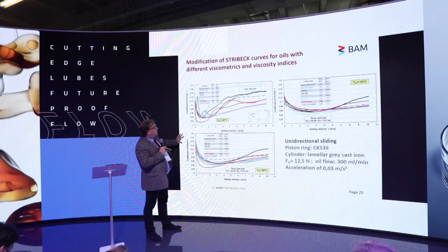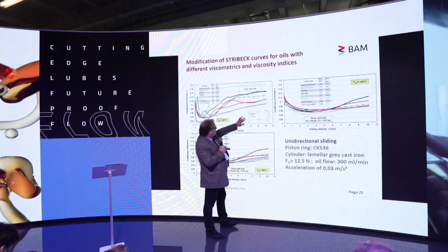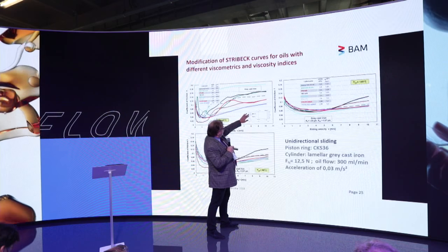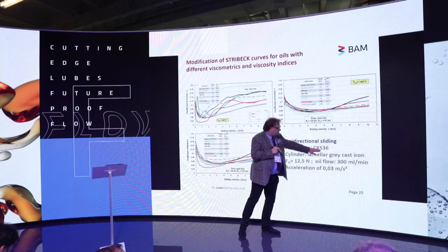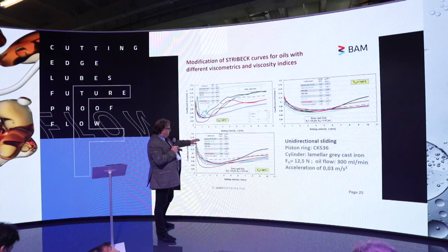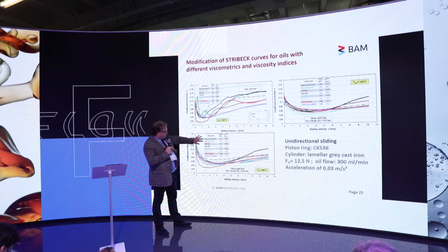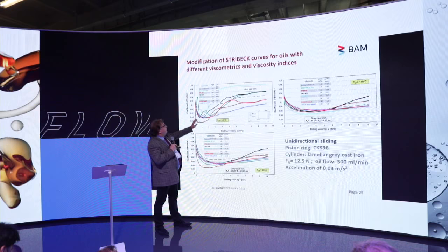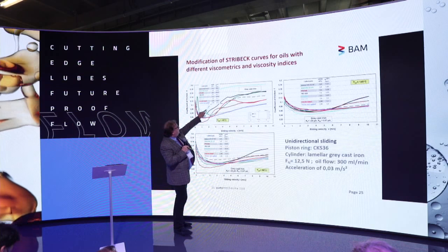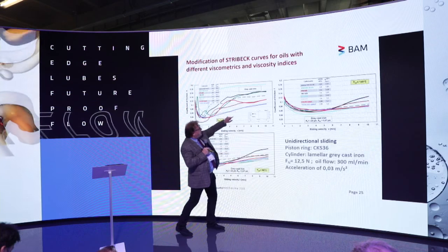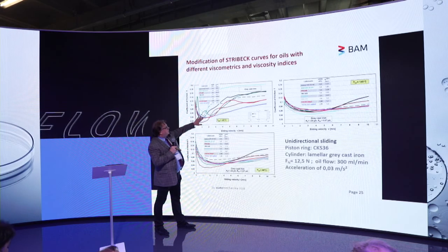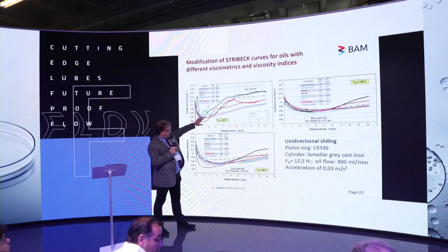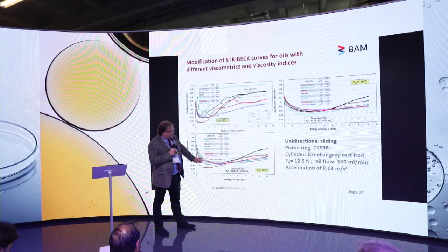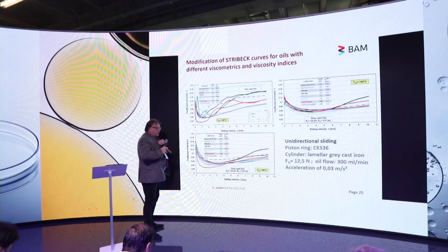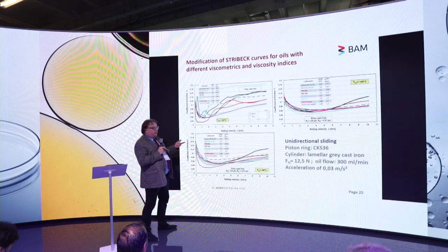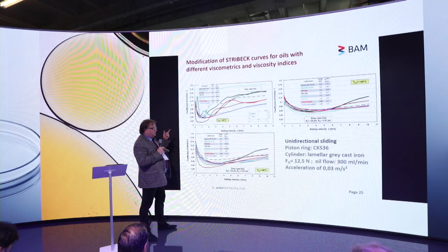What does it mean for the oils? If you look at a gray cast iron liner and a piston ring coated with a chromium alumina coating, and here you have different types of oils: factory fill oils, hydrocarbon, polyglycols. The factory fill, the gray and the green, at room temperature, high friction. You take a polyglycol, you have much lower friction at room temperature. At high temperature, the differences are not so big, but there are some differences. So changing the chemistry, changing the viscosity reduces friction for the future, but these are new chemistries.